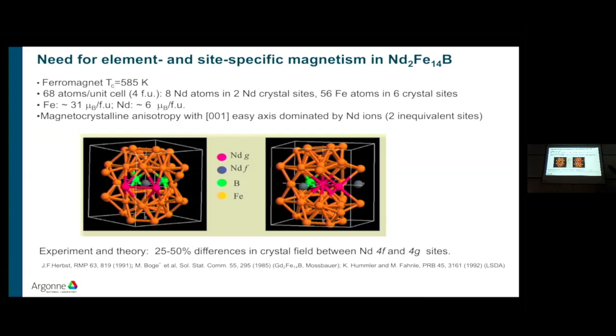Now, there's a lot of atoms in the unit cell, and most of it is iron. So if you have a magnetometry measurement or even a neutron measurement, you will see the signal mostly from iron. So we are interested in the neodymium in particular because that's what's giving this magnet its magnetic hardness or the coercivity. It makes it hard to demagnetize. So it's a small neodymium moment compared to the large magnetization for iron. So our techniques are perfect because we can tune the X-ray energy to a neodymium resonance, separate the neodymium from the iron. But we need more than that here because there are two neodymium sites that are crystallographically inequivalent.